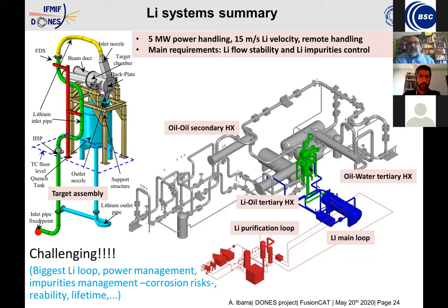We know that some properties of the lithium and the interaction of the lithium with the materials are a strong function of the impurity content of the lithium. For example, corrosion properties are a strong function of the oxygen and nitrogen content. So we need to control very carefully the impurity content of the lithium. So we need to have a purification loop in which we control the impurity content of the lithium in an online process at the same time that the impurities are being produced.